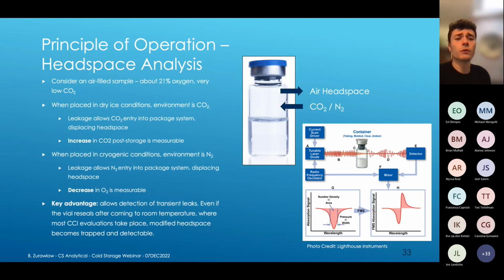Just to give some background on the principle of operation for headspace analysis, let's consider an air-filled sample with about 21% oxygen and very low CO2. If I place this sample into a dry ice environment, as would be the case for products stored at -60 or below during shipment, which typically incorporates dry ice, the environment is CO2. As that dry ice sublimates, it's going to create a CO2 environment.